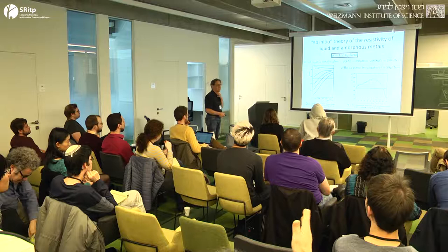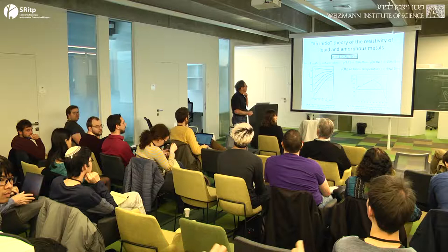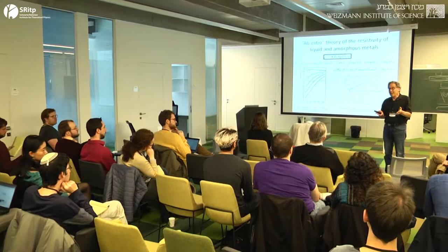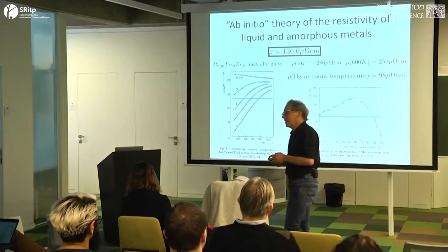Because if you take the Drude picture, for a metallic glass with one electron, very dilute, then the resistivity can be much higher. Because you are assuming one electron per atom, so the atomic distance, the Bohr radius, and the electronic characteristic length are the same. Well, no, they're more or less the same because of the stability of matter, but they're actually not that close. The typical distance between atoms is usually about 2 angstroms, which is 4 times a Bohr radius, which when I cube it is a pretty big number. It's actually quite extraordinary, I think, that this works so well.